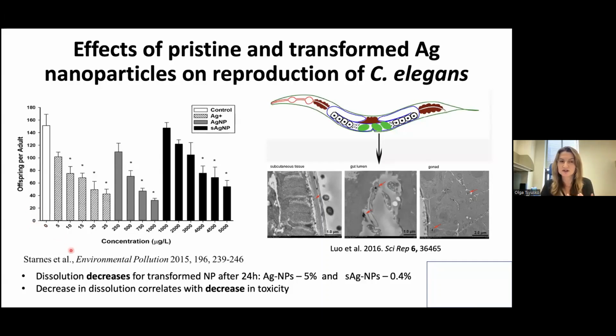As you can see, the toxicity in response to silver ions right here is pretty steep. At 5 micrograms per liter and above, we start seeing some effects in toxicity in terms of reproduction. However, the toxicity is decreasing as soon as we switch to pristine, and it's definitely even less toxic when they are sulfidized.